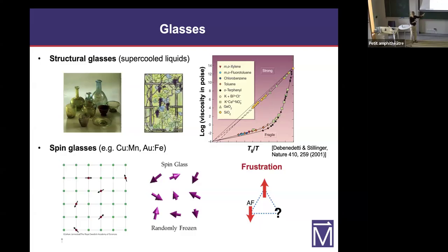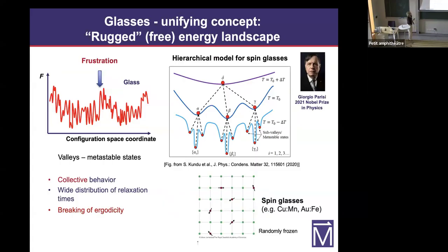It turns out that what all glasses have in common is frustration, which leads to this rugged free energy landscape where each minimum represents one metastable state corresponding to a particular configuration of the system. And these metastable states are separated by energy barriers with a wide distribution of heights and therefore relaxation times. When the system transitions from one metastable state to another, this involves collective rearrangements of the system. So the configuration is different. Because of this wide distribution of barrier heights, these are slow processes. And so on experimental timescales, the system can probe a relatively small number of states. It cannot probe this entire landscape. And this is why the system is non-ergodic and it exhibits non-equilibrium behavior.